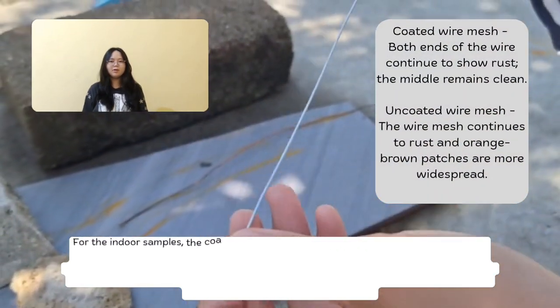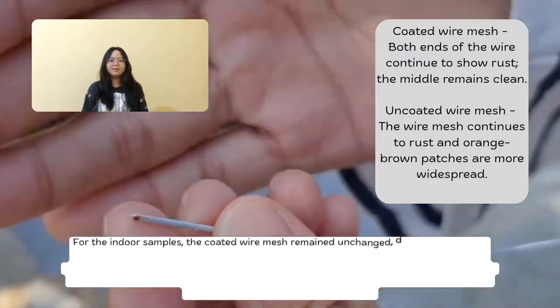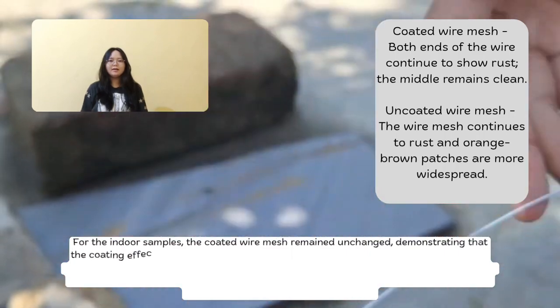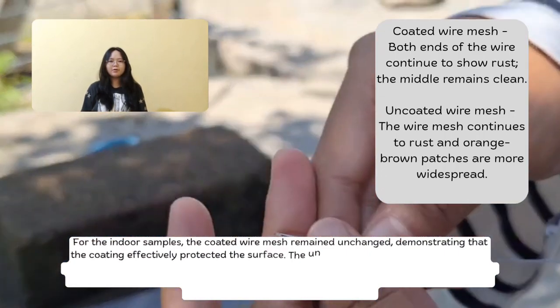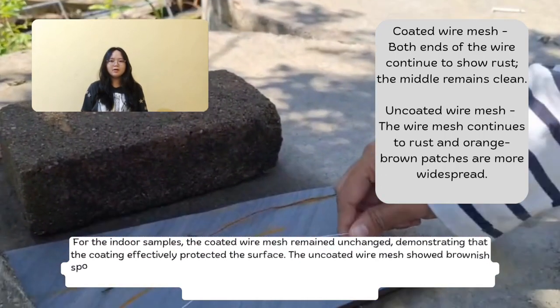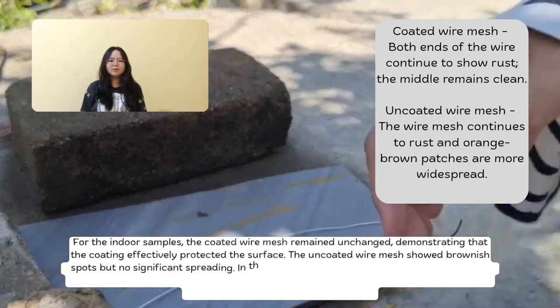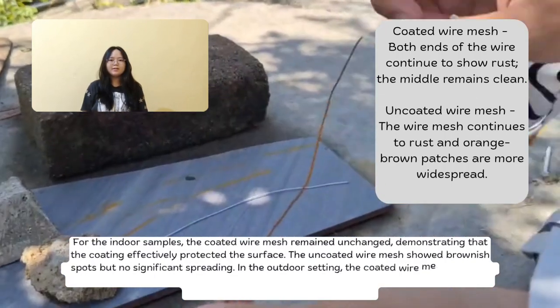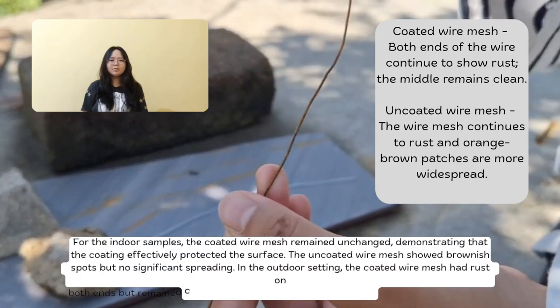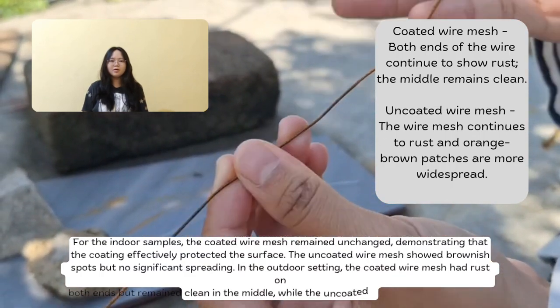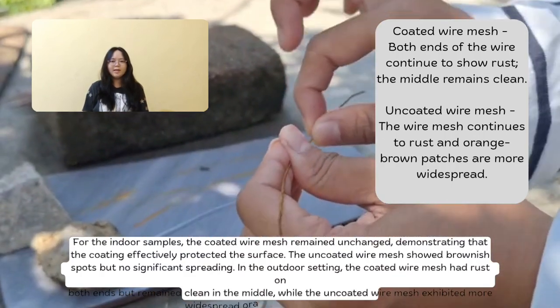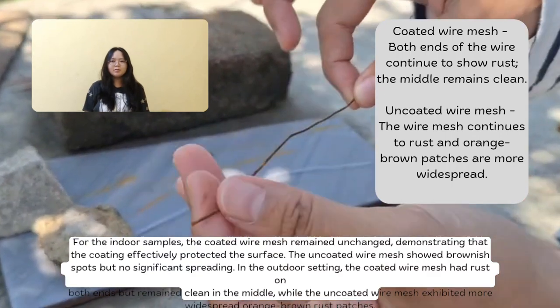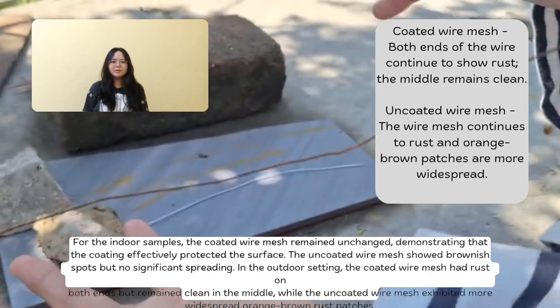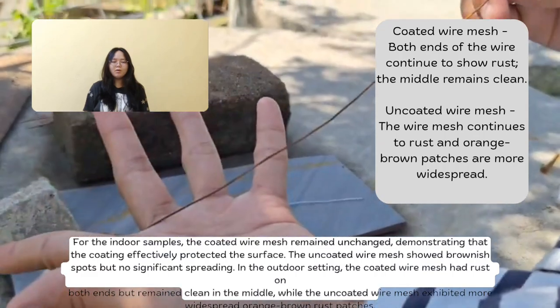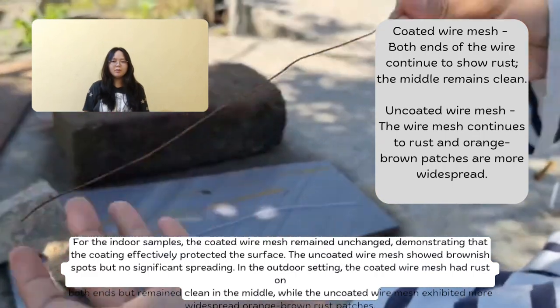For the indoor samples, the coated wire mesh remained unchanged, demonstrating that the coating effectively protected the surface. The uncoated wire mesh shows brownish spots but not significant spreading. In the outdoor settings, the coated wire mesh had rust on both ends but remained clean in the middle, while the uncoated wire mesh exhibited more widespread orange-brown rust patches.